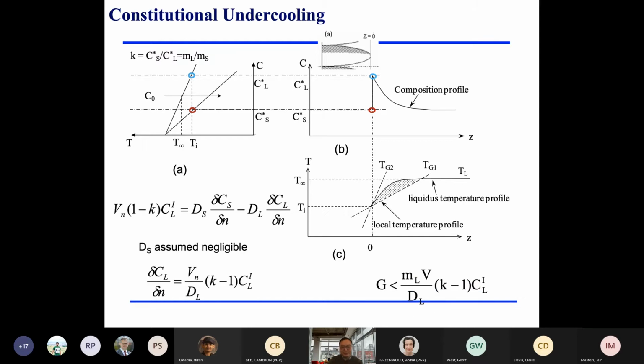the most important concept for solute dendritic modeling, right? So you can apply different thermal gradients to avoid this columnar to equiaxed transition, or promote it. For example, in directional solidification, if we want to grow single crystals, you normally use high thermal gradient, low growth velocity, essentially TG2 like that, and you would not allow any grain to form ahead of the solidification front. But if you want to promote this, for example, in continuous casting or even welding process, you can do it by introducing heterogeneous solidification, either by alloy design or by process optimization, right?